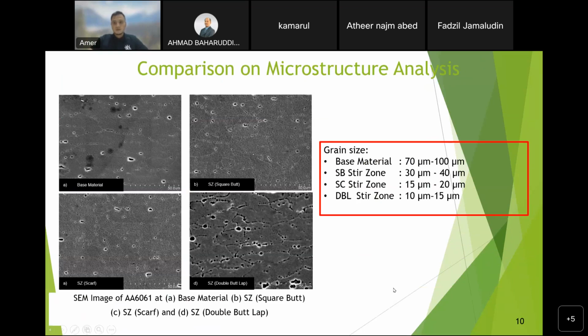As we can see, the result shows that the grain size of each joint is different at the stir zone. The grain size for the base material is 70 to 100 micrometer. For the stir zone, the square butt microstructure size is 30 to 40 micrometer.